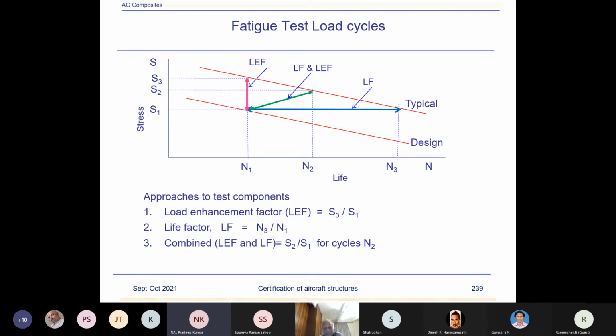Actually, this load enhancement factor and life factor, both we have to use for the composite joints. This SN curve, what you have shown, sir, in these slides, is that the SN curve for the joints or any material? No, this is composite. I'm talking about composite. But this is just a hypothetical curve. So typically, it could be for joints like a bearing failure, composite to composite joint, or open hole fatigue.